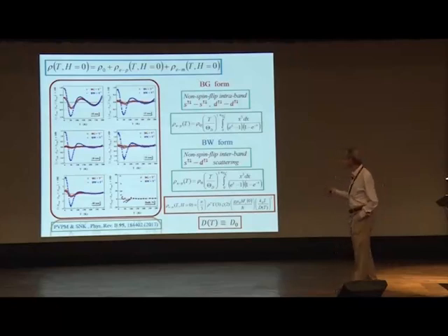Then what I'm showing you is the deviations when you have Bloch-Grüneisen and Bloch-Wilson plus a T-square term, and you see that the Bloch-Grüneisen gives you a lower percentage deviation compared to the Bloch-Wilson. It's just the reverse. And now in some cases you do see that it is not systematic.